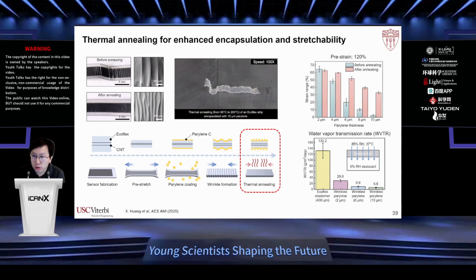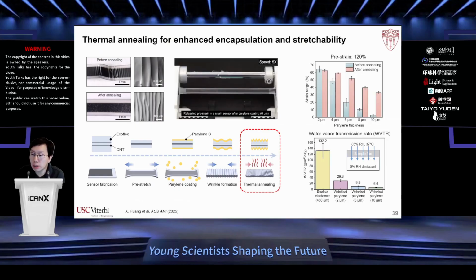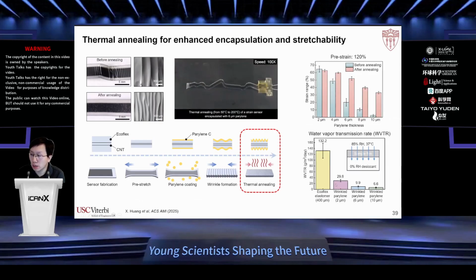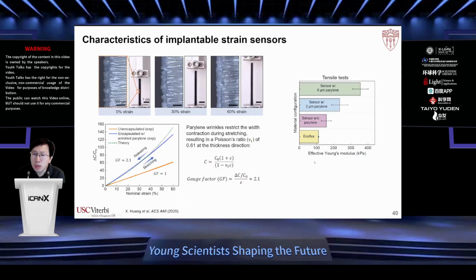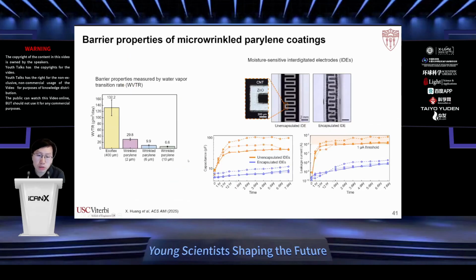So to mitigate this issue, we apply thermal annealing to reduce the parylene modulus to make it softer, so we can still form micro wrinkles even for very thick parylene. This allows us to achieve large stretchability with low water penetration, measured using water vapor transmission rate, shown here. And we show that with this wrinkled parylene encapsulation, we can achieve pretty low water vapor transmission rate.